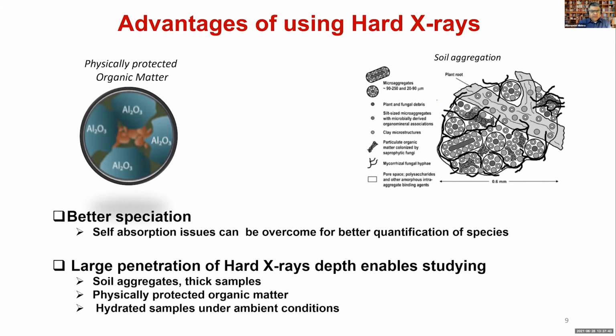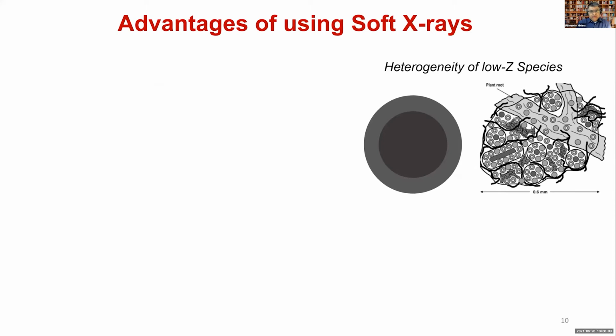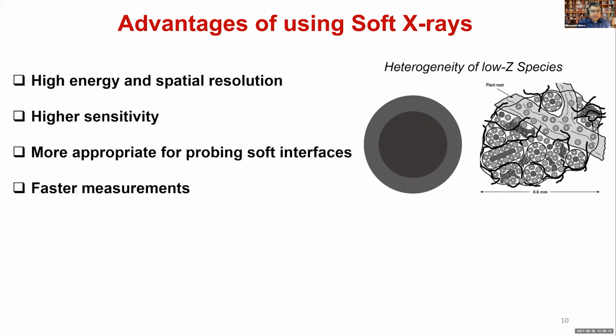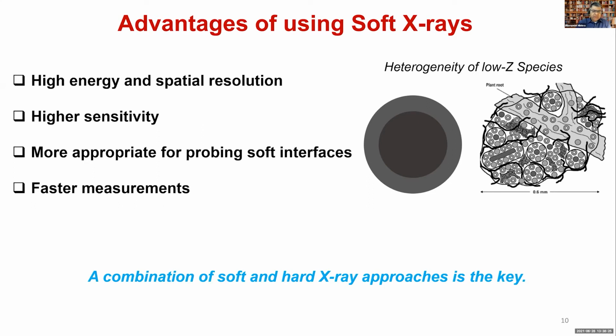So some of the advantages of hard X-rays are, of course, large penetration depth due to high energy, and hence it can punch through soil aggregates or any thick samples. It can also look through physically protected organic matter or hydrated samples under ambient conditions. And also, as mentioned, it can overcome self absorption issues for better quantification of species. However, soft X-rays have their own advantages, and heterogeneity is one of the main ones, because they have high energy and spatial resolution. They also have higher sensitivity and are more appropriate for probing soft interfaces. It's a faster measurement. So really, it's the combination of the soft and hard X-ray approaches that should be the key.